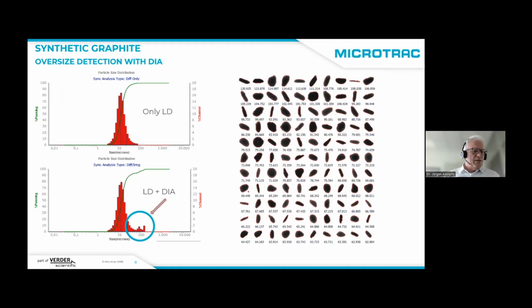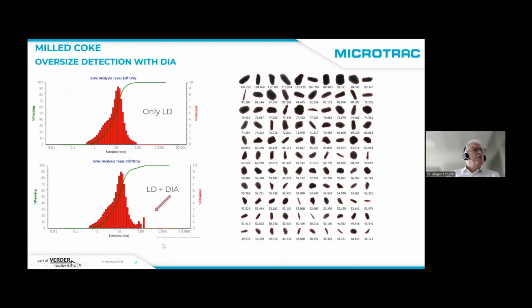There's another thing to remember, the statistics for laser diffractions are very high, and for this reason, you will not be able to determine the few of these oversized particles, but with less good statistics of the dynamic image analysis, you can see this, and then we can add here. Another example is for a milled coke. We have only the laser diffraction in the upper part around 10 microns. And again, with the dynamic image analysis, we see then particle size also over the 100 microns. They are also shown in these pictures here.